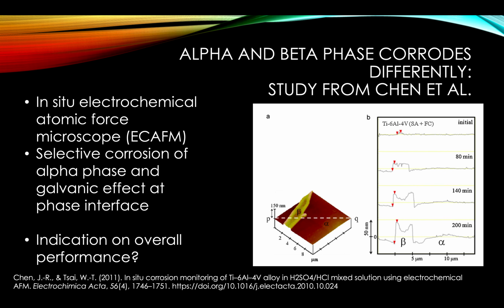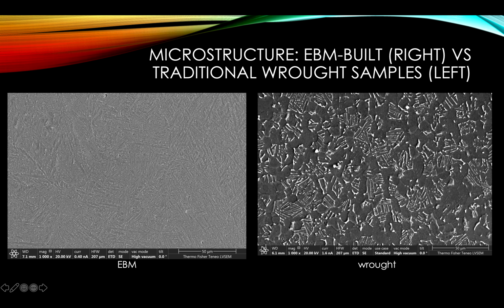So here is an interesting study from Chen et al. They performed an in situ electrochemical atomic force microscope study within these little cells. And you can see that the alpha phase actually corrodes faster than the beta phase, and the galvanic effect is observed near this interface. So what can this indicate on the overall performance? Let's look at this microstructure.